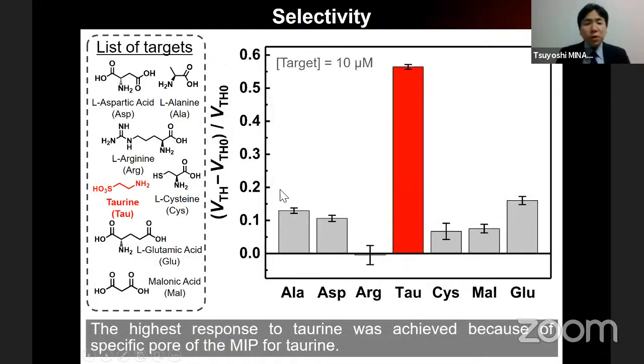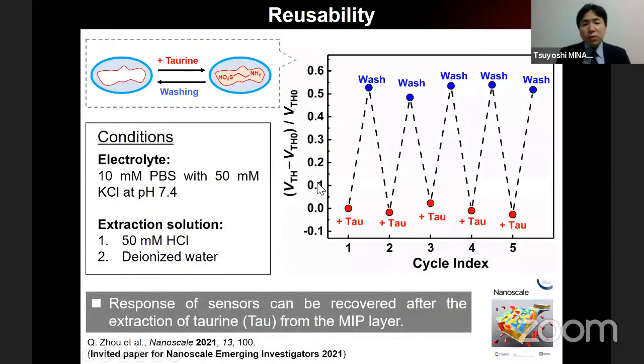The selectivity is also important. In that case, taurine shows the highest response compared with the very similar other components. That means this is not from physical adsorption. We can detect it through the MIP's selectivity. This is also washable and reusable. After we immerse it in the taurine solution, we extract it with hydrochloric acid and deionized water.